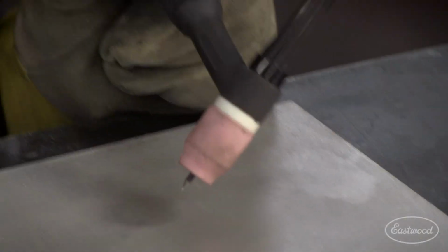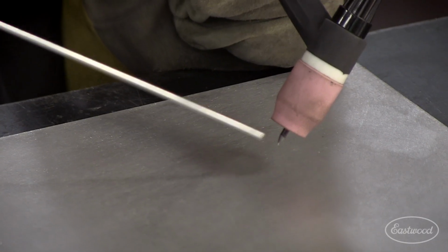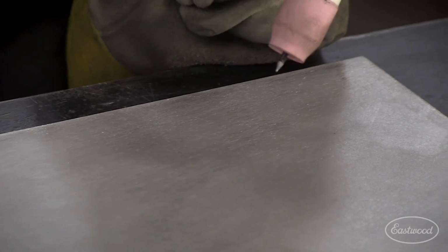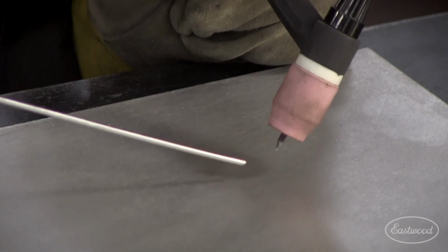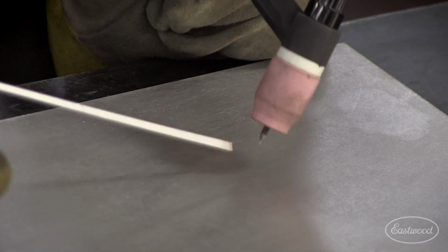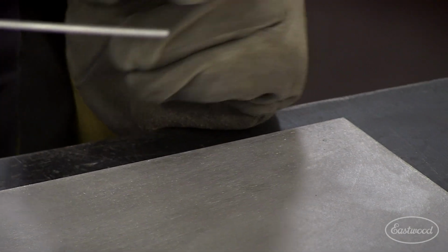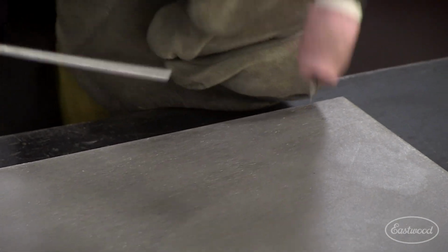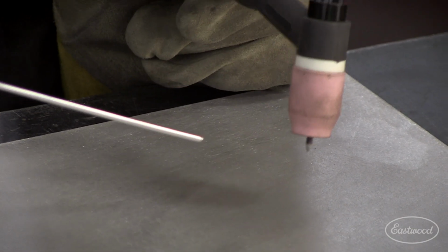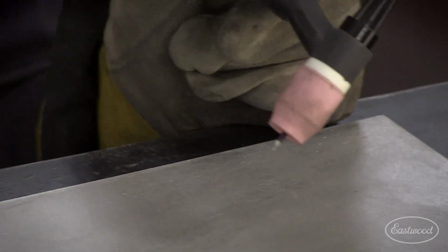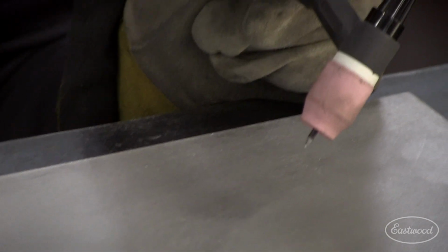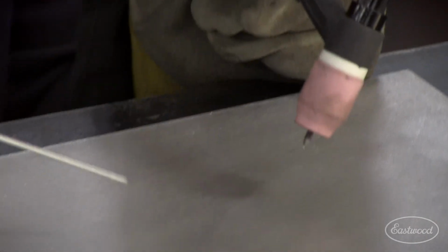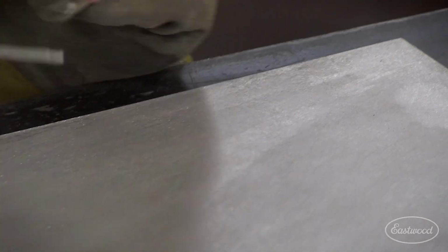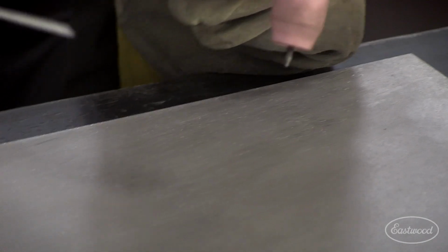If you get too sharp of an angle like this, what's happening is you're shooting the arc off here, which is bouncing off, and it's hitting your filler rod that's waiting to dab in the puddle. If you start welding aluminum and your filler rod's balling up on the end before you even go to dip it into the puddle, that means that your torch angle is too sharp. You're turned too far in. It's reflecting off the panel, putting more heat into the panel, and it's melting your rod before you even dip it in.